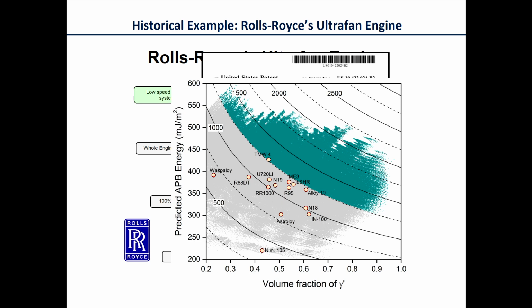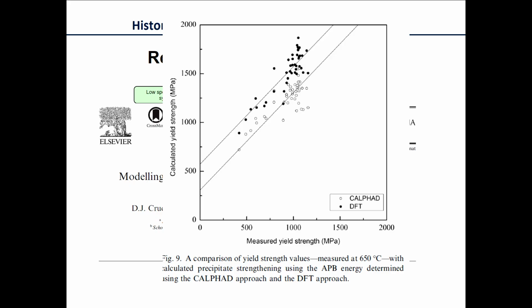Existing available powder disk alloys, we believe, are somewhere on this contour plot, somewhere here. And of course, we were able to design new compositions to sit in this space slightly outside it. This was, again, the concept which was used for the alloy we designed. We published some information about this. The models were not completely perfect, but you can see here that when we compared the measured strength against that predicted by different kinds of computational methods, not a bad correlation here. Not great, not perfect, but good enough to allow us to make estimates that were able to cut down the amount of experimentation needed.